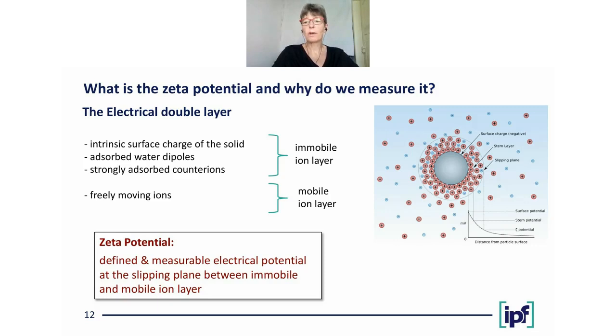And these ions adsorb to the solid surface and form an immobile layer on the surface. This may also include larger molecules like polymers or surfactants. And you have this strongly adsorbed ion or molecule layer on the solid surface. It's called the immobile ion layer. And you have more ions around in the solution. They can move freely, and that's why they are called the mobile ion layer.